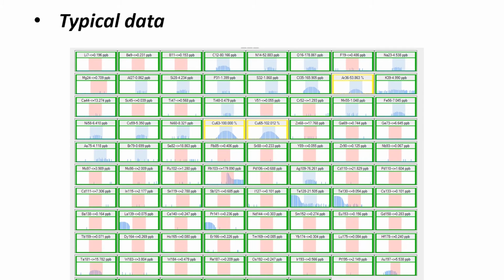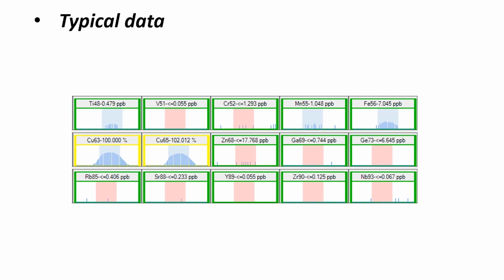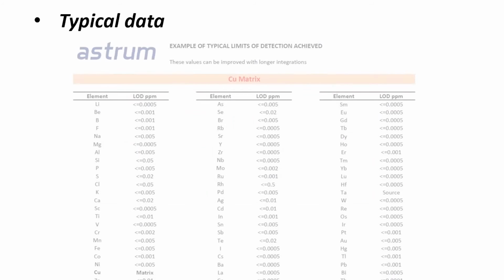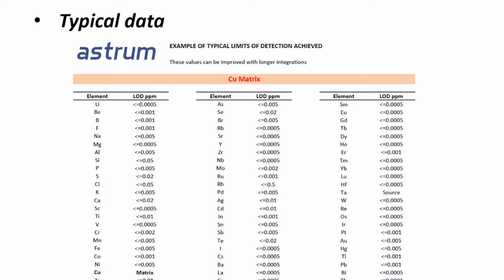Now onto typical data from the GDMS. Here we have a mass scan from lithium to uranium of a high-purity copper sample, where data has been recorded for matrix element and all traces. If we focus on one part of the results, we can see that they are displaying a few ppb to sub-ppb values. Overall, the results achieved show many elements with ppb or less detection limits, and purity of 4, 5, and 6N are easily achieved.